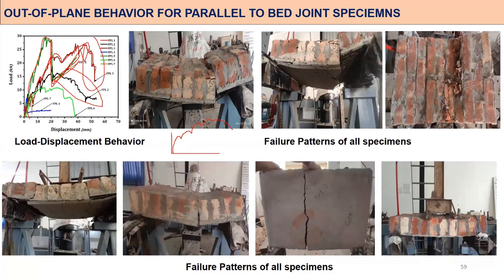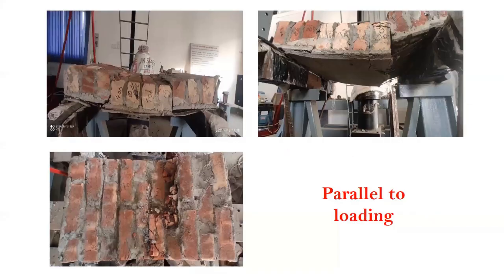Now, we can even apply a pre-stress. When we use pre-stress, we can get a uniform amount of gain and drop in the load. Again, here you can see failure in the support regions, and your geogrid actually peeled off from the surface because the displacement is about 60 mm, which is very huge for masonry structures. So obviously FRP is a wonderful material. We experienced a support failure similar to the previous case. This is a closer view: the force is applied like this, the crack occurred here, and the textile delaminated from the surface at the topmost region of the failure.